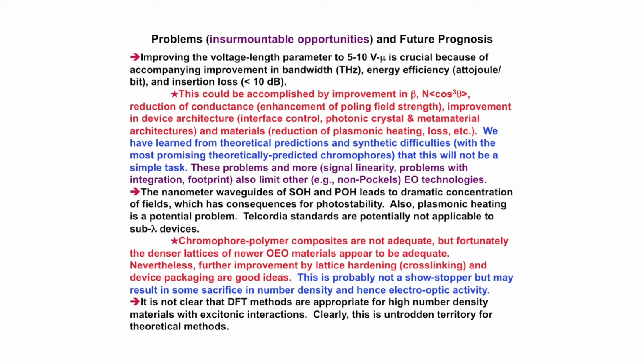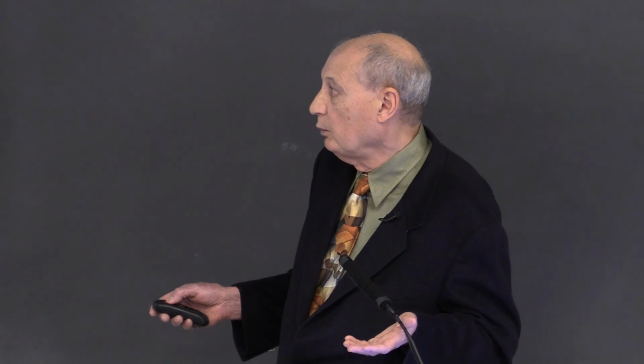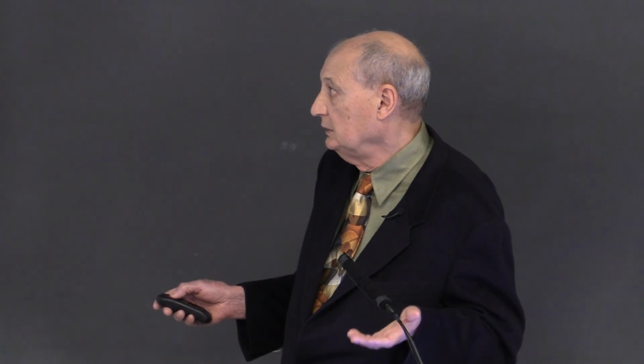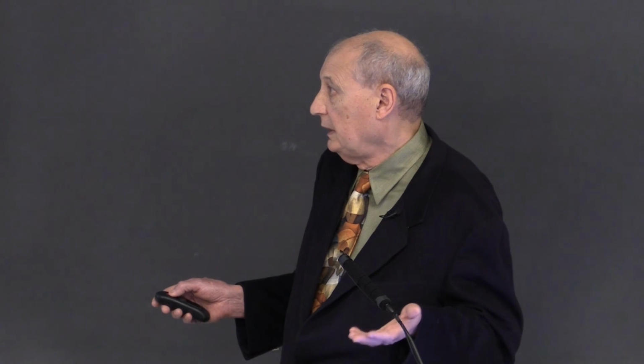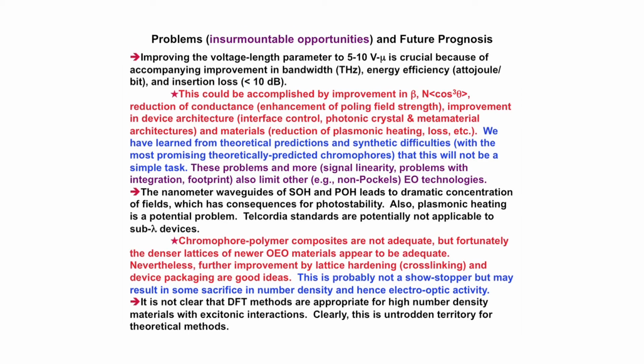The other problem that we need to be aware of, which isn't really a problem yet, but it could be, is that these nanometer dimensions of our plasmonic-organic and silicon-organic hybrid devices lead to dramatic concentration of fields. And these high fields could conceivably create photostability problems. This hasn't been a problem yet, but it may be well that we actually think about lattice hardening to deal with this if it becomes a problem. Plasmonic heating is, again, a potential problem. Now, we note that this hasn't been a problem yet, and it probably isn't a showstopper, but we need to be aware of it.